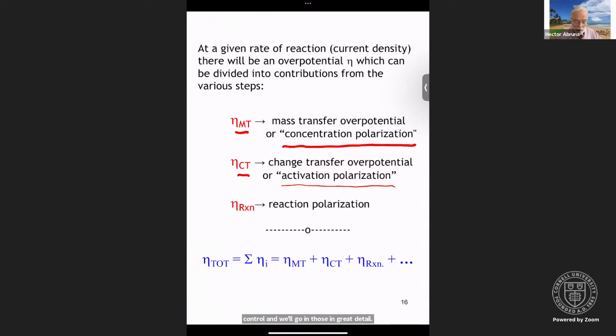You can also have a quote unquote reaction polarization. For example, if your system involves a pre-equilibrium that generates the redox active species, or there's a subsequent electron transfer reaction, all of these things will contribute an effective overpotential to the reaction. And clearly, the overall or total overpotential will be the sum of the individual contributions. So here we have mass transport overpotential, charge transfer overpotential, reaction overpotential, and however many other terms you want to include in your expression here. But the basic idea is that this will dictate what the overall overpotential is in your system.